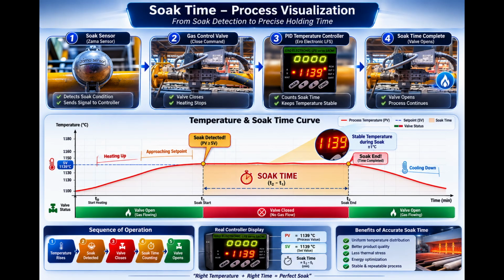Reaching the target temperature is only part of the firing process. The most critical stage begins during what engineers call soak time. This is the period when the kiln holds its peak temperature for a carefully controlled amount of time. During soak time, several important changes take place inside the ceramic body. The clay particles continue to sinter. The material becomes denser. The glaze melts, flows smoothly across the surface, and develops its final appearance. Internal stresses are gradually relieved, and the entire tile reaches a more uniform temperature. This allows the ceramic body to develop its final mechanical strength.